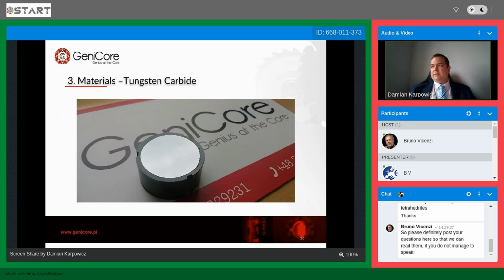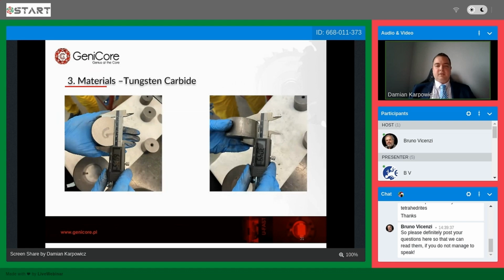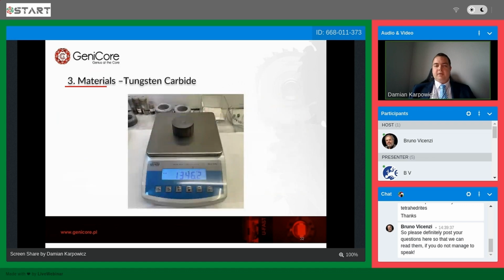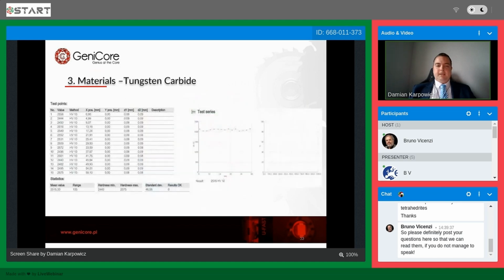This is specifically a project where we worked for our customer in China, the second biggest tungsten carbide producer, and they asked us to provide a device which will allow them to produce tungsten carbide with very high density and hardness, 60 millimeters in diameter, 30 millimeters in height. So quite a big volume, almost 1.5 kilograms of tungsten carbide, and we achieved it. We provided both the device and the sintering process technology to allow them to start the production immediately after commissioning.